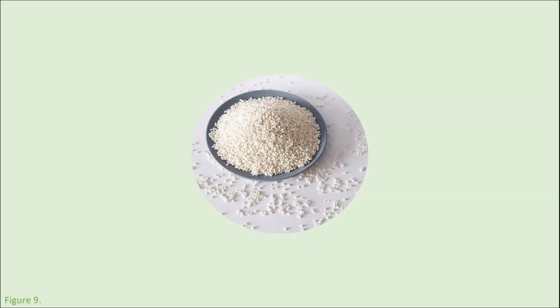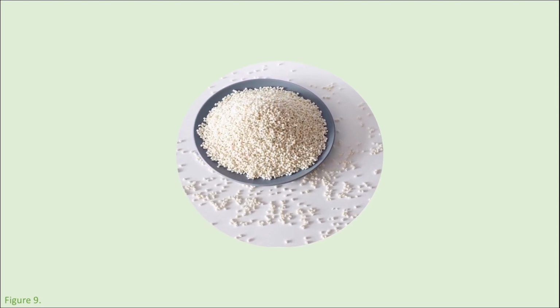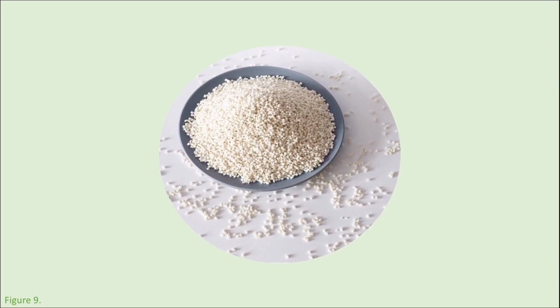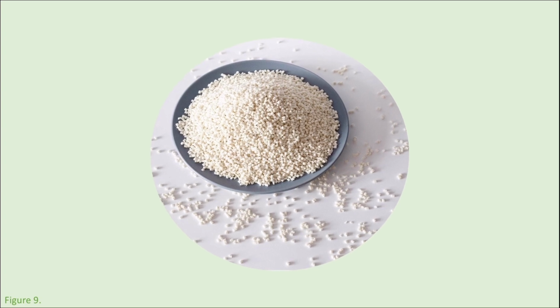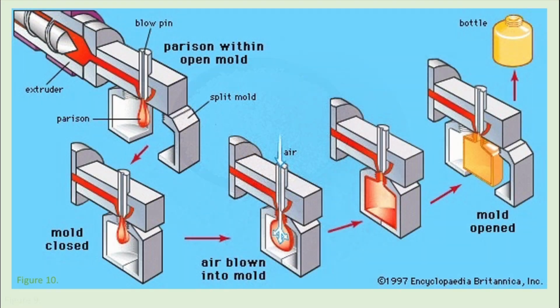Once synthesized, PLA can easily be processed through melt processing, where PLA resin chips are heated above its melting point of 180 to 200 degrees Celsius, depending on the chain length. This means it can easily be made into different products and behaves like many other plastics used today. PLA can be cast into components, injection stretch blown into bottles, as shown, or cast and extruded into films and sheets. Furthermore, PLA has a great benefit of being clear, so it's ideal for single-use packaging.